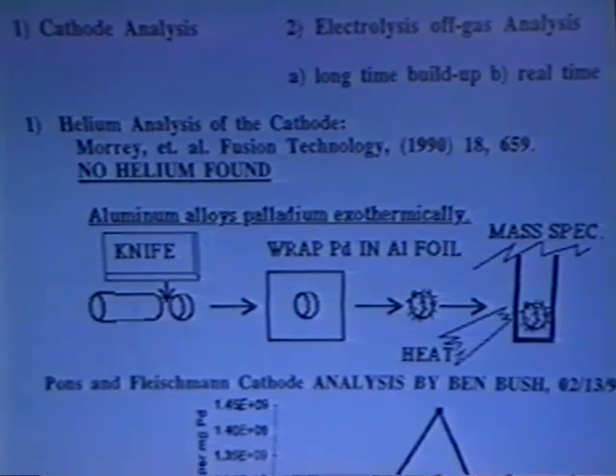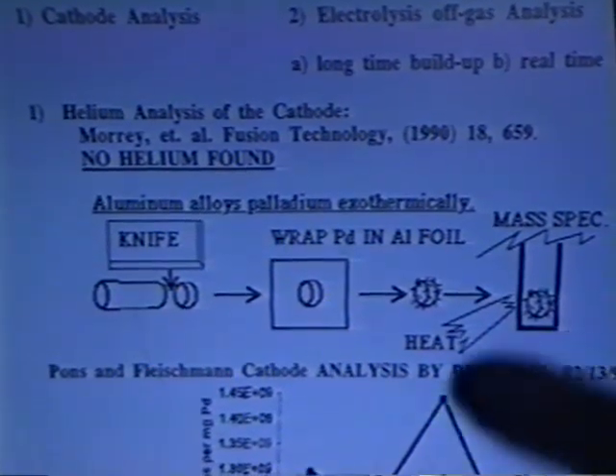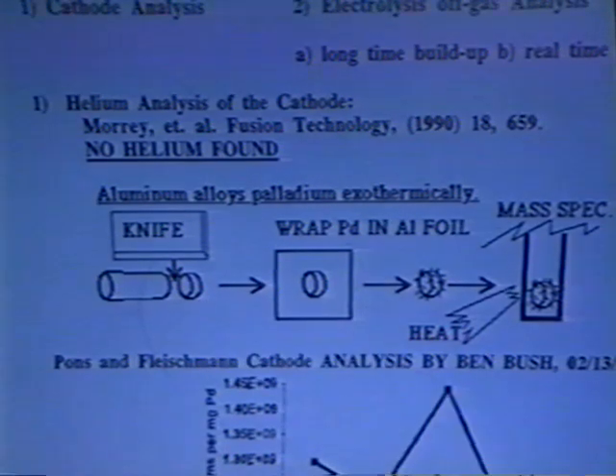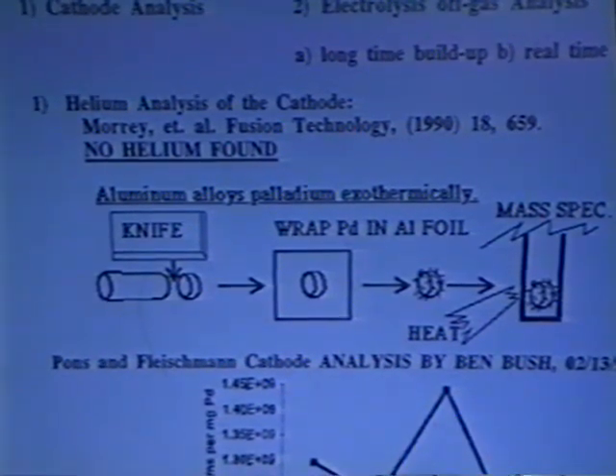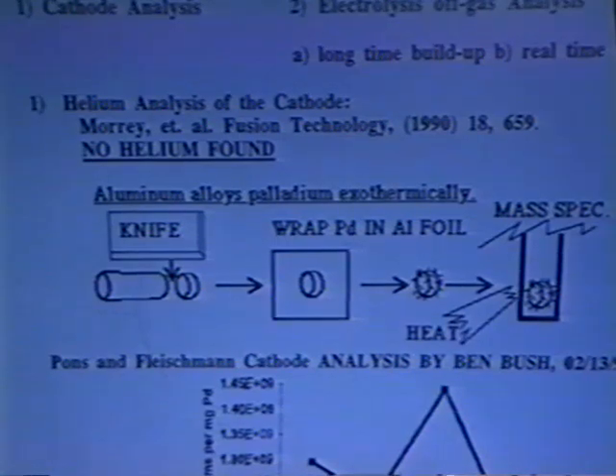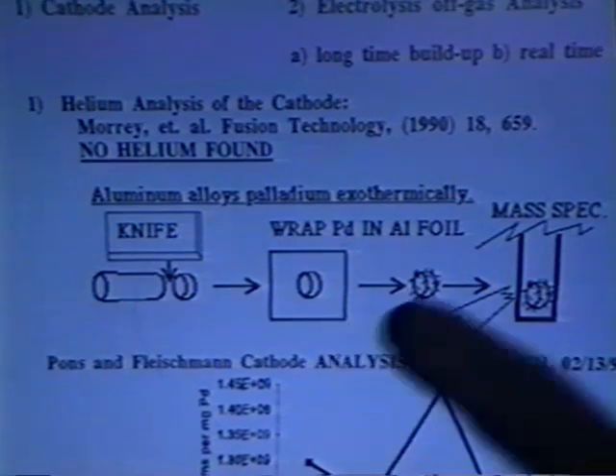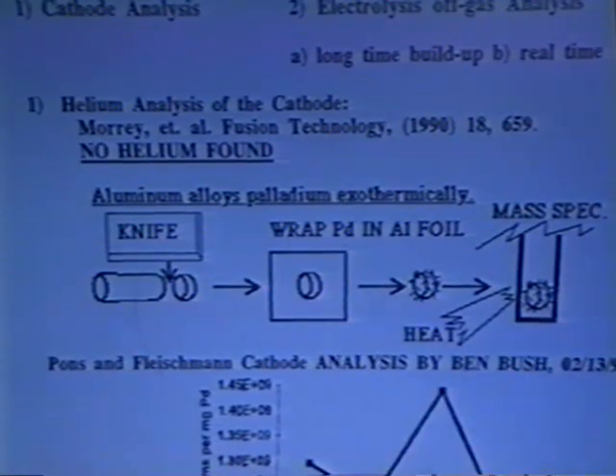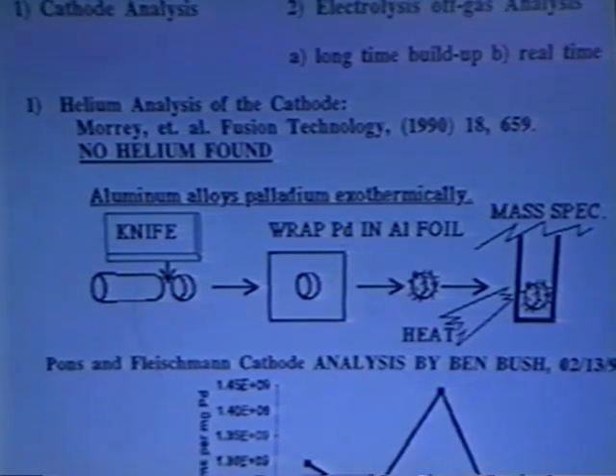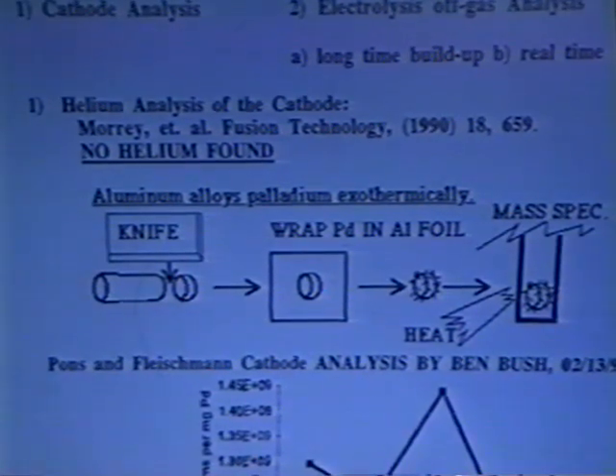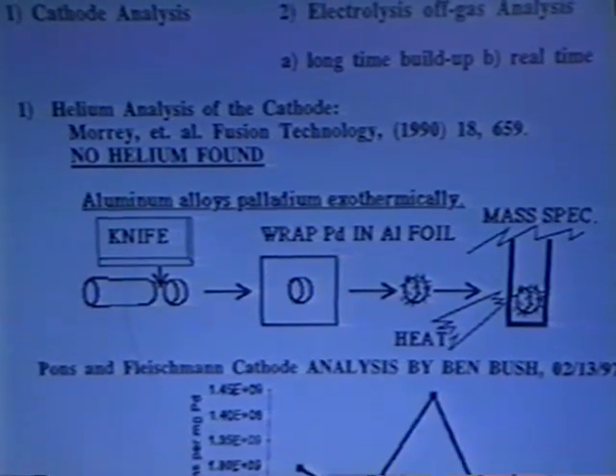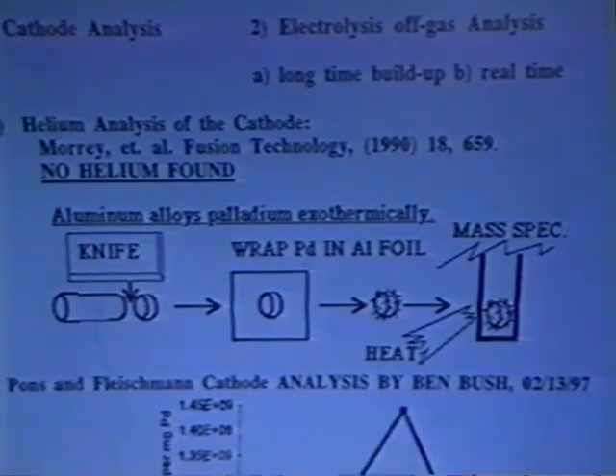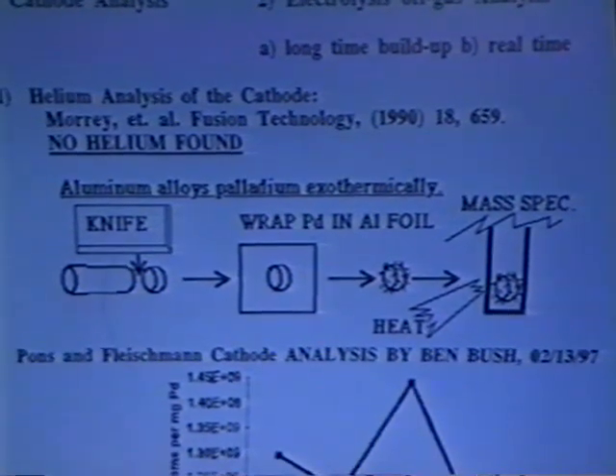You can do that by wrapping a bit of aluminum foil around a piece of palladium. You cut it off with a knife. You need to use a new knife blade because you don't want to transfer helium-bearing palladium from earlier cuts to the piece you're cutting. So anyway, you wrap that piece of palladium in aluminum foil and then put it in your mass spec system and heat it. And the aluminum foil will alloy exothermically with the palladium, thus melting it. And since you melted the metal, you've released the helium into the mass spec.